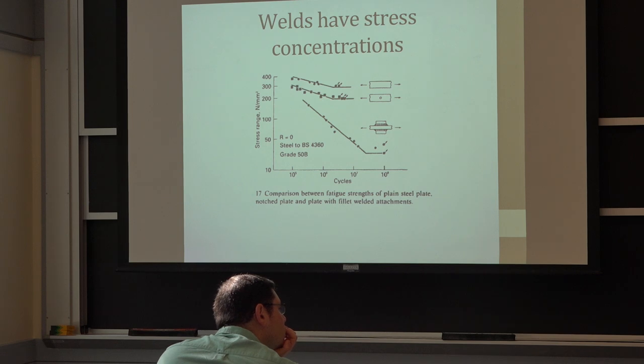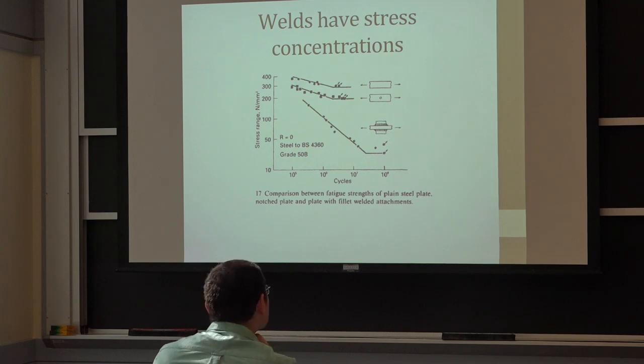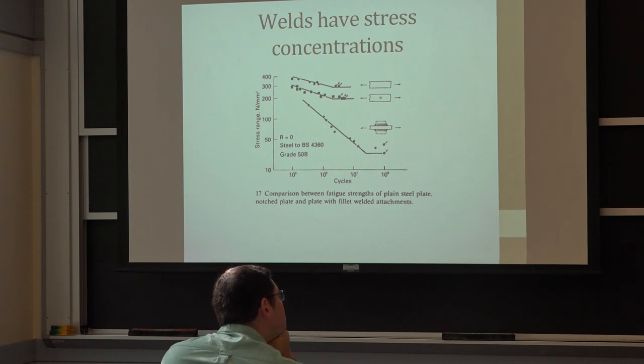You might as well make it out of 36 KSI steel rather than 100 KSI steel. In fatigue strength, welded structures are all equal. Lousy. Okay? Because of stress concentrators. Now, there's some things we can do to try to improve it, but they tend to be fairly expensive. But basically, people who don't understand this will pay the price.